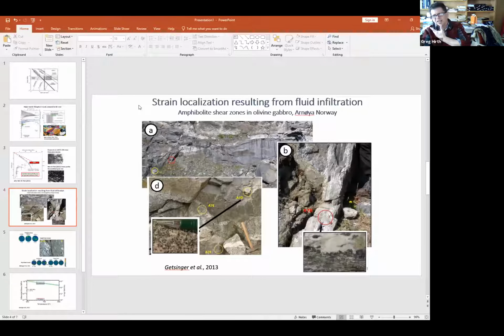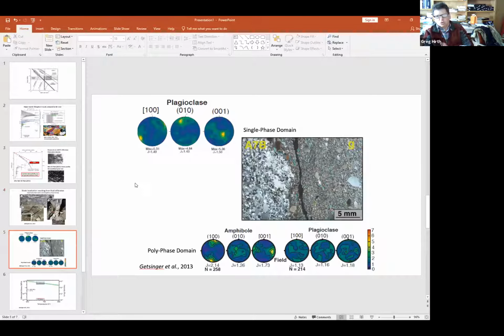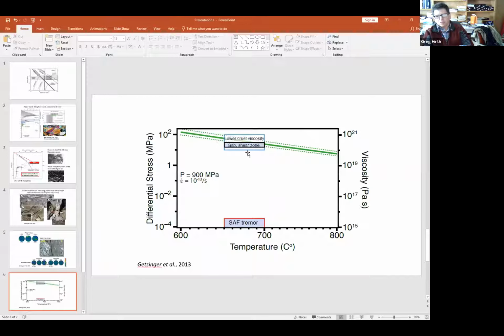Another thing that Andy's results provided was a bound on what the viscosity in the lower crust could be. There's a lot of debate about viscosity contrast at the crust mantle boundary, and geodetic data are one way of looking at that. Another way is to look at rocks that are deformed at the lower crust. You need to go to special places to find those rocks. In this case, we went to look at a shear zone in the lower crustal exposures in Norway, where all the strain is localized in a region where water infiltrated the lower crust. We did the tricks that we do to look at the deformation textures in this rock, and what we came away with was an estimate of viscosity of something like 10 to the 20, or maybe a little bit bigger than that.